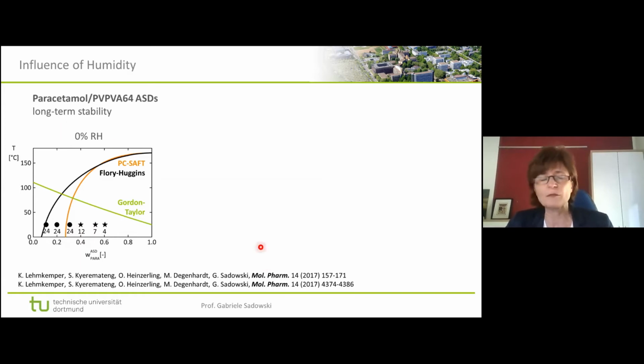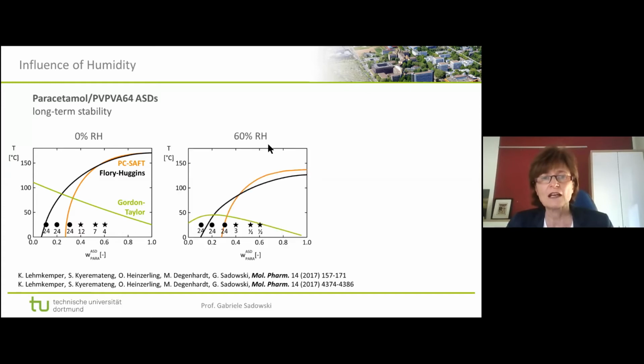So we have different storage chambers. We have a lot of storage chambers in the meantime, hundreds of samples stored there at different conditions. And of course, one of these conditions is 60% relative humidity, and this is again 25 degrees centigrade. You see our prediction. So the solubility lines are of course affected by the fact that the relative humidity is higher than on the left-hand side, but also Tg. Tg is very much affected, particularly on the left-hand side of the diagram where a lot of water is absorbed. So water is a plasticizer, and that means it decreases Tg drastically from dry conditions to 60% relative humidity. That's why we have a maximum here. So the Tg is going down, particularly on the polymer-rich side, because here we have a huge amount of water.